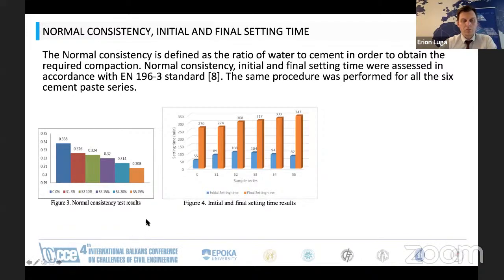Actually, it's a good thing, but this is not general for slag, because generally slag is finer than cement and requires more water than cement alone. So in this case, this local slag has some different properties. Maybe the grinding is not as fine as in general.